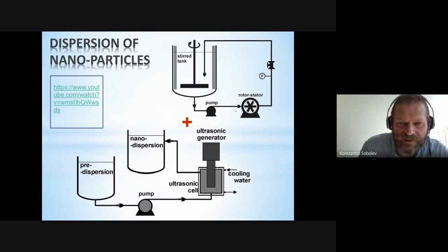And obviously, the high-speed mixing and rotor stator type of geometry was used to disperse nanomaterials. Sometimes it is not really working extremely well. So ultrasonic dispersion is something which is commonly used, and dispersion times can be relatively long. We speak about potentially 2 hours, 3 hours dispersion times.